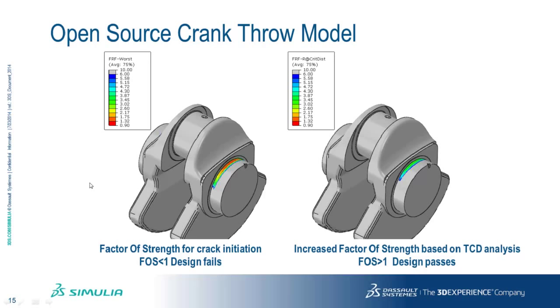If we just use the surface stresses and do the life to crack initiation, this component fails. We need to reduce the stresses to achieve the life that we want. But if we then recalculate our safety factors based on subsurface stresses, the stresses at the critical distance, then our factor of strength is greater than 1. And so this design now passes. And it passes because we are accepting that initial cracking and saying we're going to base our design on non-propagation of those cracks.